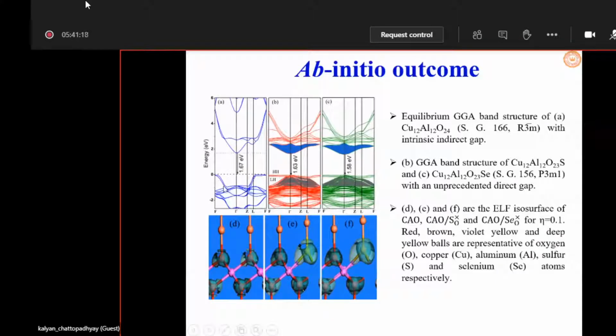Second, you see that the valence band is basically a flat one, indicating that the holes are heavy. That means, as we have seen from our simple qualitative discussion, hole mobility will be very low. So this is also supported by the band structure. Here you have heavy holes, and the density of states at the Fermi level is also very low.